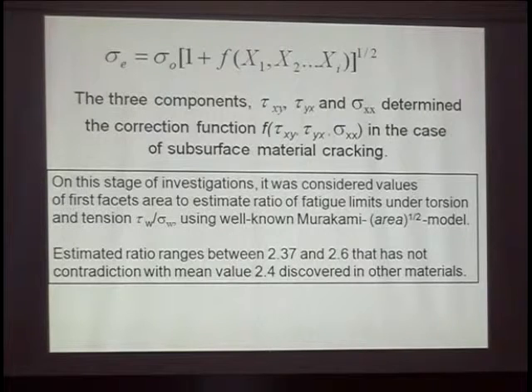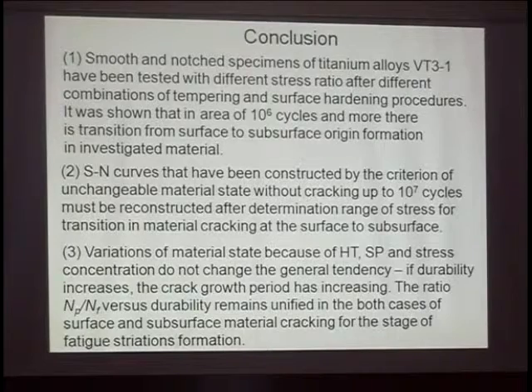But it should be clear that subsurface there exists not only one but several origins. So a summarizing case should be introduced for estimation of material gradient subsurface. For titanium alone there exist maybe 3, 4, and 5 origins with approximately the same area. That is why knowledge about the manner of summarizing area subsurface for material gradient should also be introduced. So here is the conclusion. First of all, the investigation has shown that really in the area well known as the area of the fatigue limit, in reality there is a bifurcation area for transition from one manner to another. It should be exactly estimated for material cracking or the manner of crack origination.